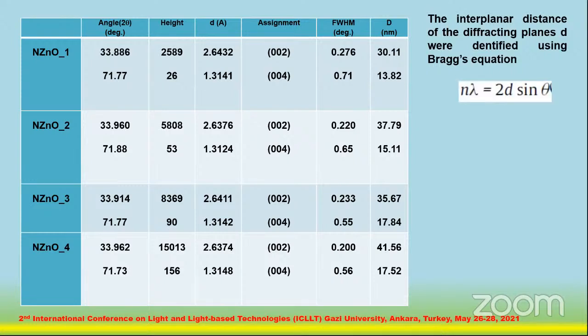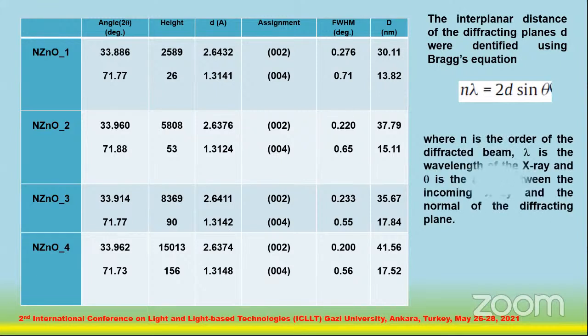The interplanar distance of the diffracting plane D was identified using the Bragg equation, where n is the order of the diffracted beam, lambda is the wavelength of the X-ray, and theta is the angle between the incoming X-ray and the normal of the diffracting plane. The grain size and the crystalline quality increase with the increase of film thickness.